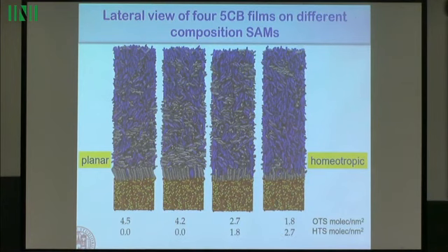So you could reduce the density of the brush, but that's not so easy to do experimentally. The other trick that we thought of, and which is actually used by experimentalists, is to have a mixture of long and short brushes, and you put them at full coverage. But since you have these short brushes, they will create kind of holes that will align the pencil, the molecules. And if the molecules do penetrate, they actually straighten the angle.